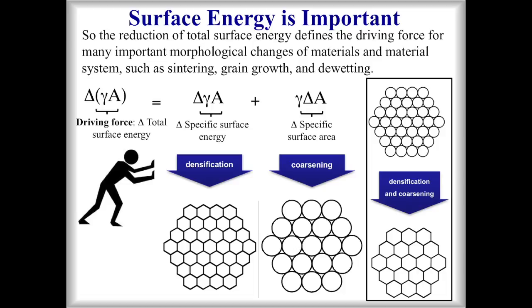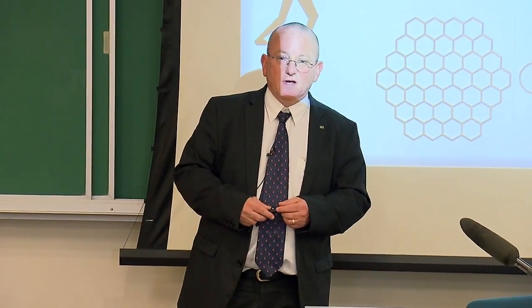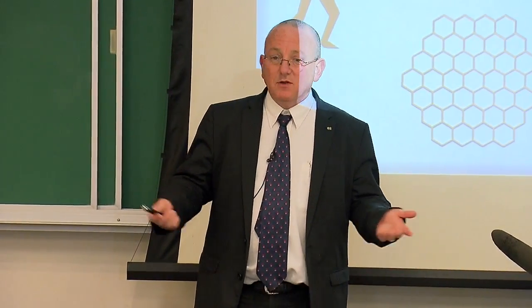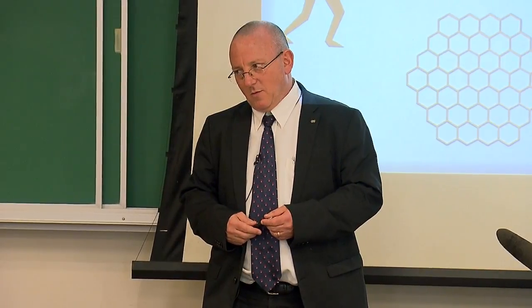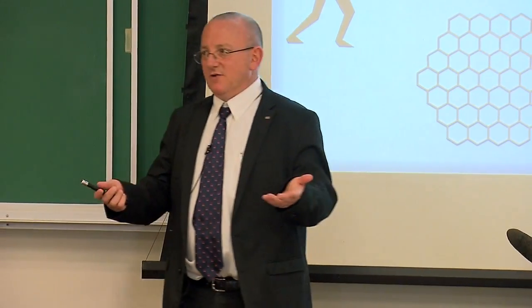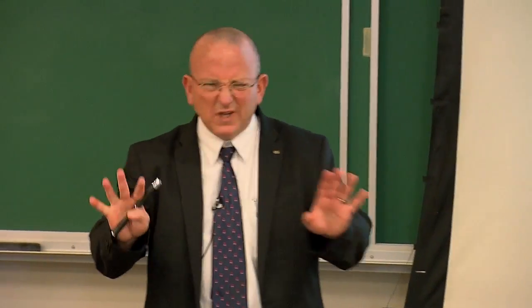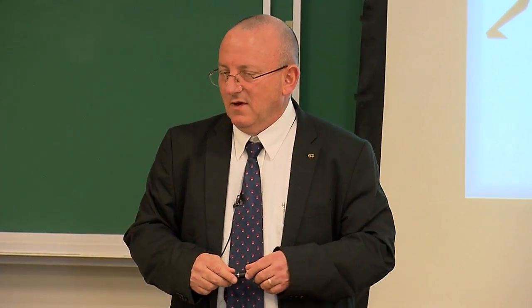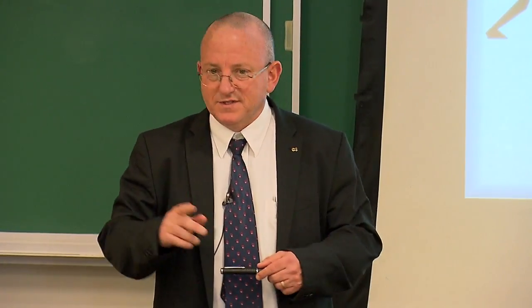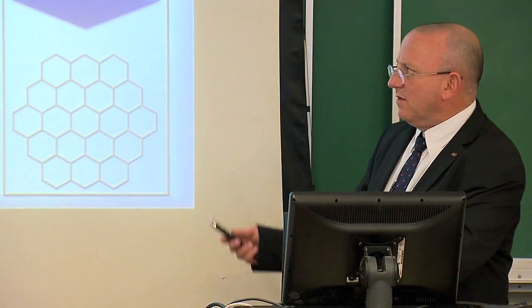Actually, I learned this lesson the hard way by trying to revisit the problem of sintering silicon carbide. There's this age-old question about why you have to add carbon and boron, an argument in the literature for a long time. And we decided to play with this in the TEM and try to figure this out. And of course, the problem with silicon carbide is that the surface oxidizes, and you get silicon oxide. And silicon oxide has an extremely low surface energy, certainly lower than that of silicon carbide. So while the system wants to reduce the surface energy by oxidizing, it's a bulk oxidation actually, so it's not really just surface, it kills the driving force for sintering. So the trick is, of course, to reduce the silicon oxide. And that's the role of carbon, and partially that of boron. So these are important concepts.